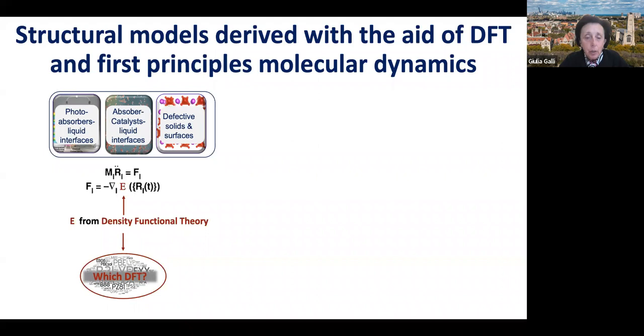And the other thing that I would mention is that very recently, teaming up with Michele Ceriotti at EPFL, we also did some calculations coupling first principle molecular dynamics with the path integral, and specifically with the quantum thermostat that Ceriotti pioneered, to look at specific electron-phonon interaction and quantum vibronic coupling for some light systems like carbon-based systems.